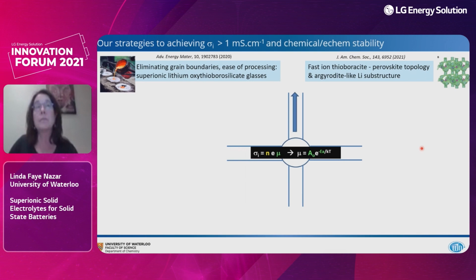So in my group, we're working on a lot of different strategies to achieve a benchmark of greater than 1 millisiemens per centimeter. That's because we need that, especially at the cathode, but also for the separator. And also achieving chemical and electrochemical stability of these materials. And it's, of course, difficult to achieve all of these simultaneously. I remind you here of the equation for ion conductivity, where we worry about the number of carriers and the mobility, where the mobility is defined by a pre-factor and an activation energy.